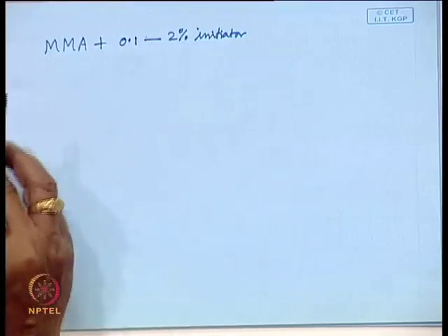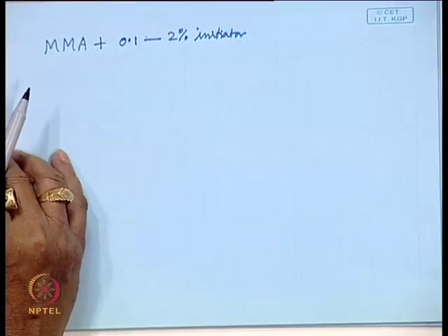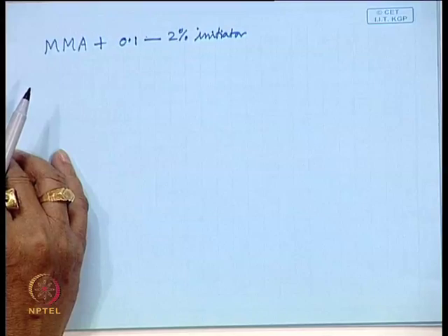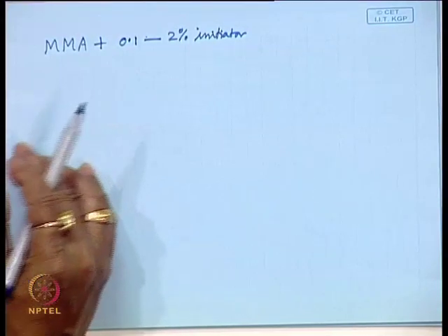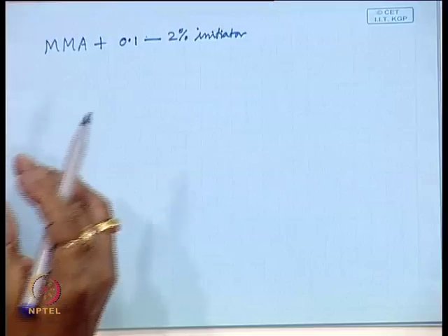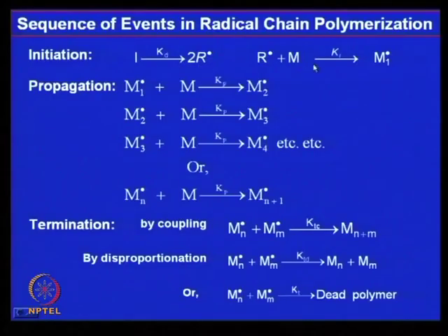A few of those molecules will break initially, and not all at the same time, they can break slowly depending on the availability of bond breaking energy from the thermal source. So, simultaneously a large number of initiator molecules can decompose into free radicals and a large number of initiated monomers will be formed. Okay.